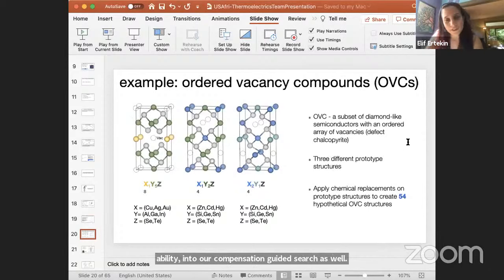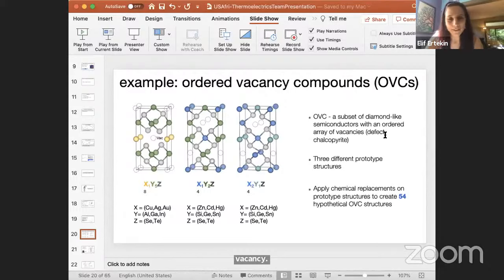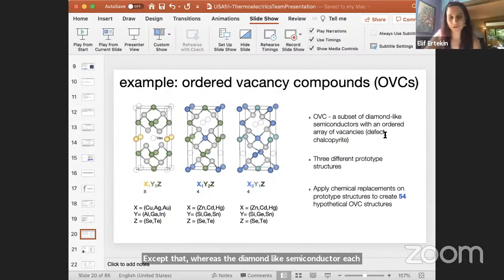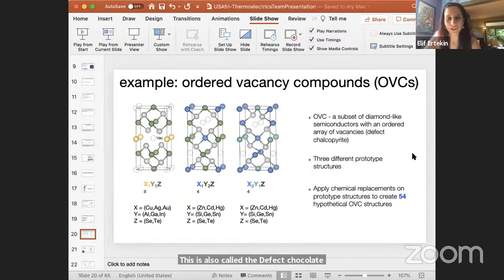Okay, so let me give you an example of some of our screening approach at work. We'll look at one family of materials, these ordered vacancy compounds, or OVCs. OVCs are a subset of diamond-like semiconductors, except that whereas in a diamond-like semiconductor each atom has this nice sp3 type tetrahedral coordination, in these ordered vacancy compounds there's a regular ordered array of vacancies that disrupts that network somewhat. This is also called the defect chalcopyrite structure. In these ordered vacancy compounds, the telluride versions in particular appear to have low thermal conductivities, but then the benefit of this diamond-like or sp3-like bonding also tends to be associated with very dispersive valence and conduction bands and generally good carrier mobilities. So they're good candidates for thermoelectrics, which is why we decided to focus our search efforts on these.